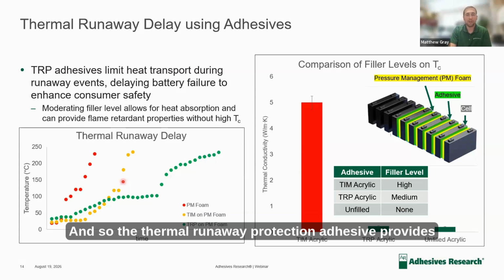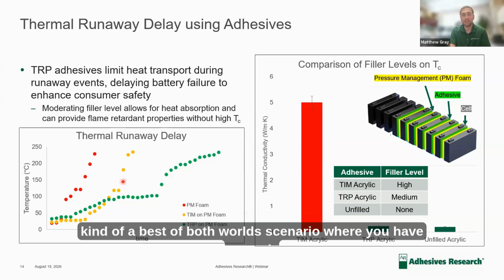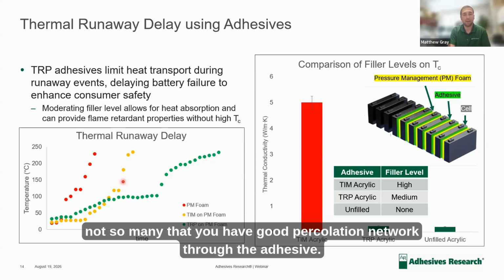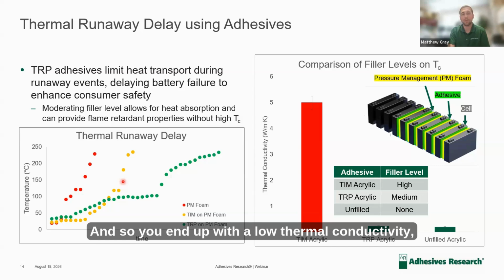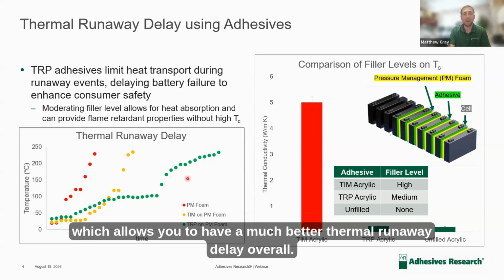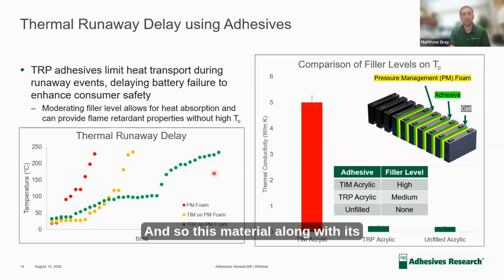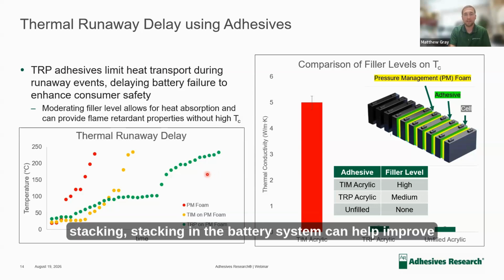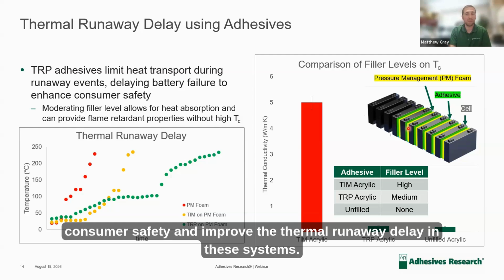And so the thermal runaway protection adhesive provides kind of a best of both worlds scenario where you have enough fillers to provide a significant thermal runaway delay, but not so many that you have a good percolation network through the adhesive. And so you end up with a low thermal conductivity, which allows you to have a much better thermal runaway delay overall. And so this material, along with its stacking in the battery system, can help improve consumer safety and improve the thermal runaway delay in these systems.